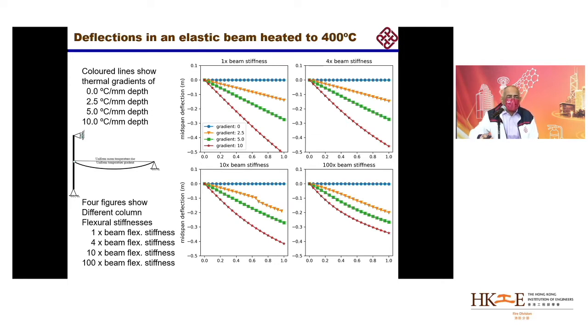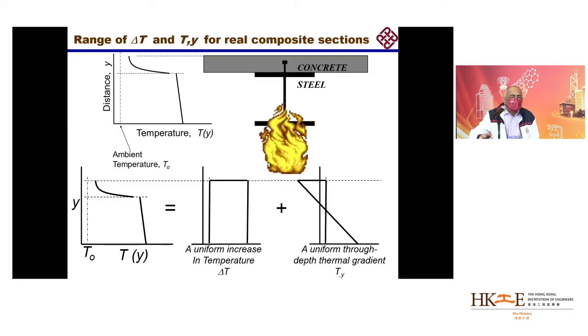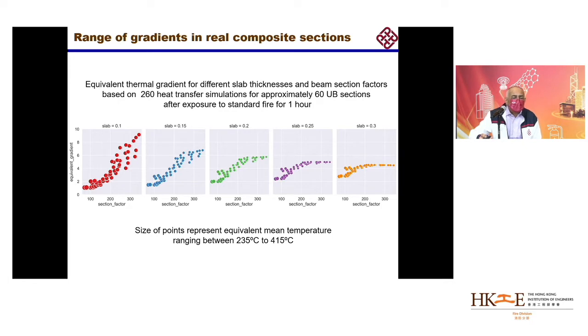Again, this is deflections for the same case. Now, if we want to see whether those situations happen in real beams, this is some analysis we did where we looked at 60 universal beam sections and applied them to 1 hour standard fire exposure and looked at the actual gradients that happen. You can see that we used from 0 to 10, so the whole 0 to 10 range appears. At the bottom is the section factor. If the section factor is high, that means the perimeter is large and volume is low, so the section is more like thin.